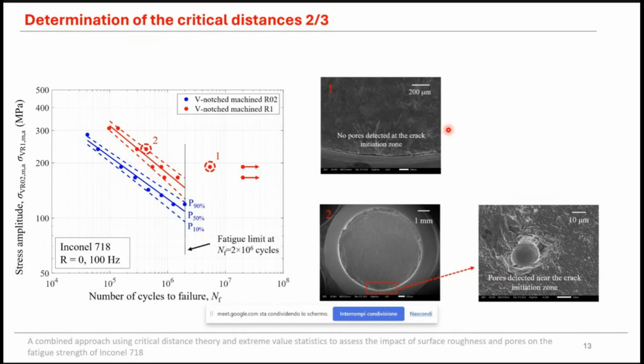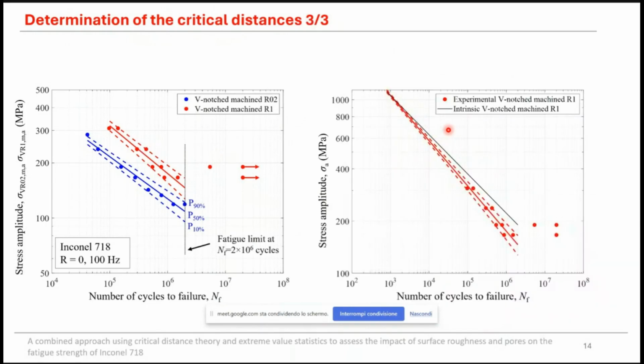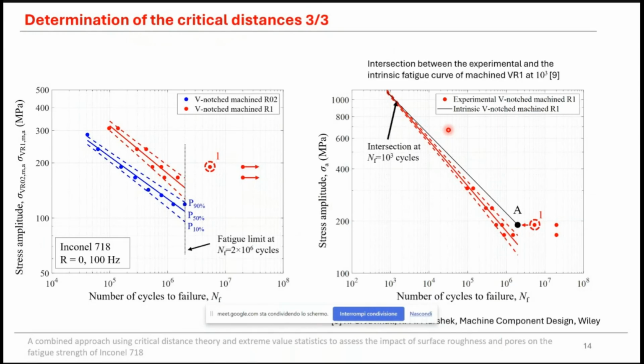So we needed to reconstruct the intrinsic fatigue curve of the blunt machined V-notch specimen, and we tried to do this following a simplified approach. We considered that the specimen indicated with 1, where no pores were detected at the crack initiation zone, gave the fatigue limit of the intrinsic fatigue curve, and then the rest of the curve was reconstructed considering the assumption proposed, for example, by Juvinall, thus by considering an intersection at 1000 cycles between the intrinsic fatigue curve and the experimental fatigue curve of the blunt V-notch specimen.